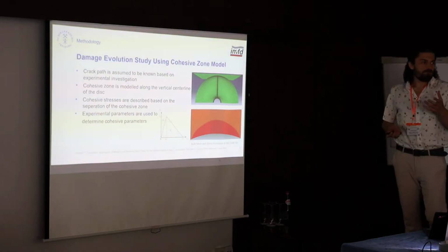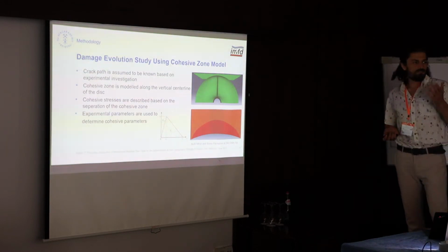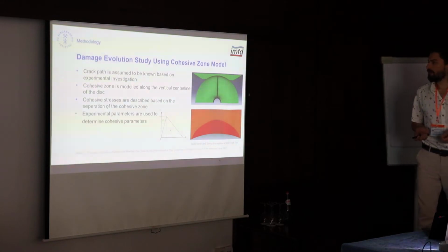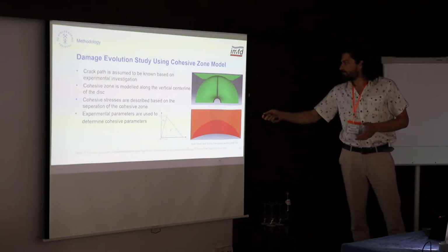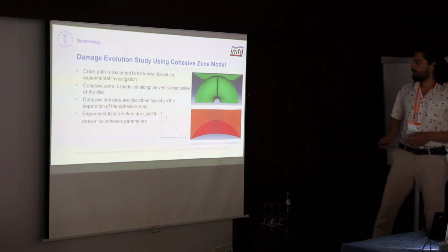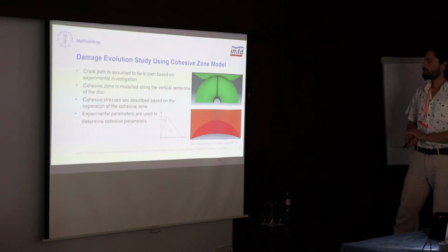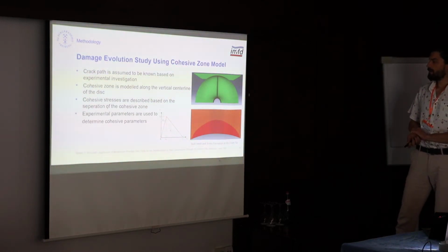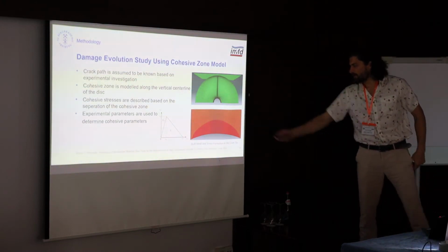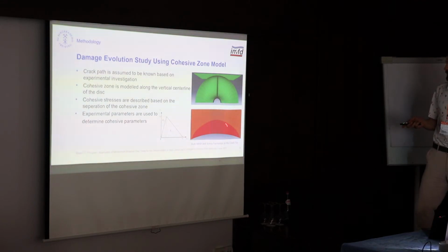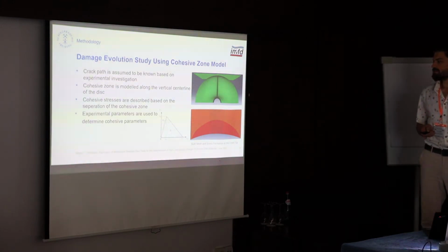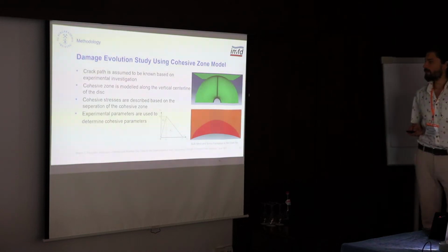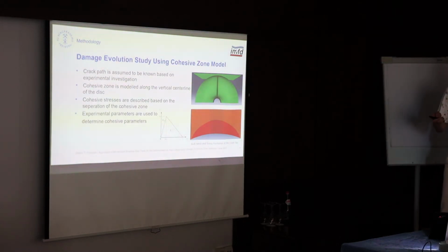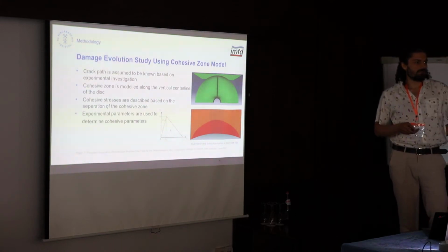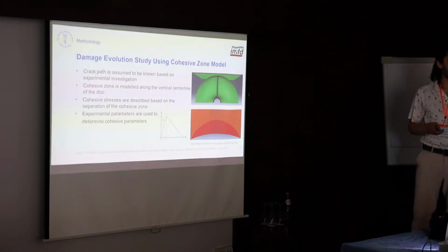So I talked about the predictability of the crack path, which is the main criterion for application of the cohesive zone model. And so I modeled my cohesive elements along the vertical diameter of the model, and then you can see also the formed stresses around the tip of the hole. I used a bilinear cohesive law for my model, and therefore assuming that the tractional stresses are the stresses that cause the failure of the material.